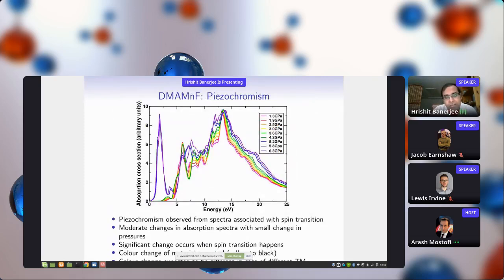With dimethyl ammonium manganese formate, we see that with small changes in pressure, you see a change in the absorption spectrum, and a large jump when there is a change from 4.2 gigapascals to 5.2 gigapascals, since this is where the color change happens. The very observable color change happens in this material, and this is very different from the color change in dimethyl ammonium iron formate and hydroxyl ammonium iron formate. So the color change here from the absorption cross section, we can assume to be yellow to black. However, we cannot say this very definitively merely from an absorption cross section.